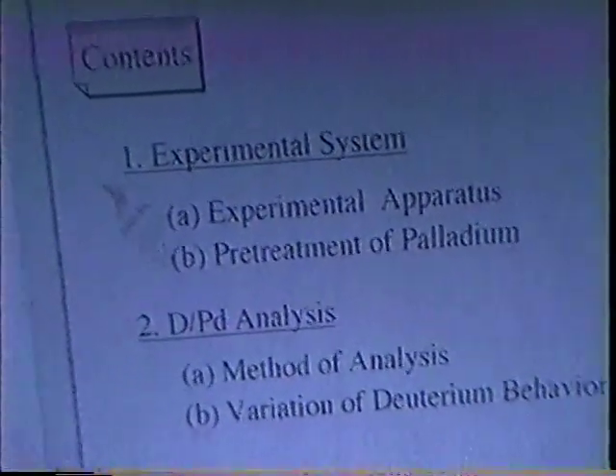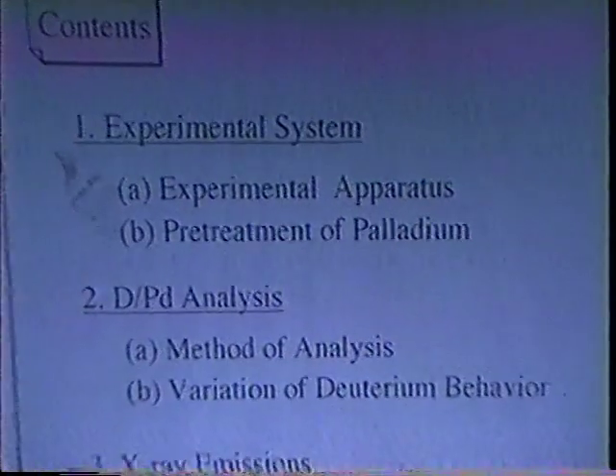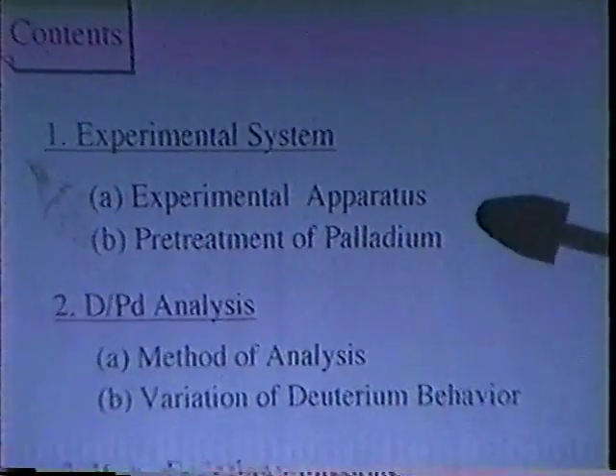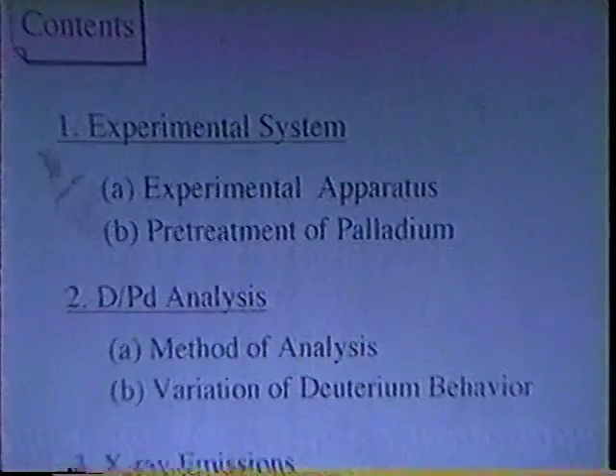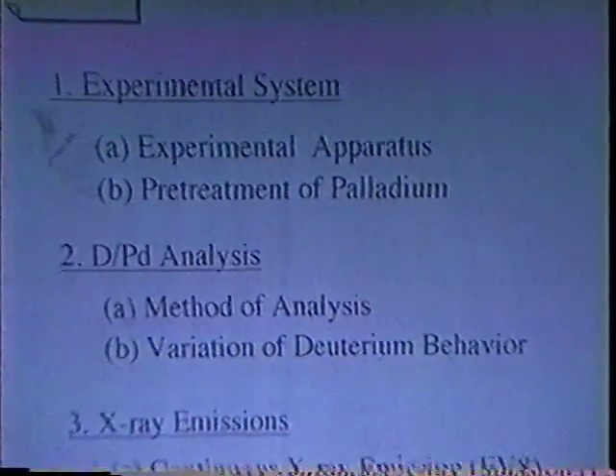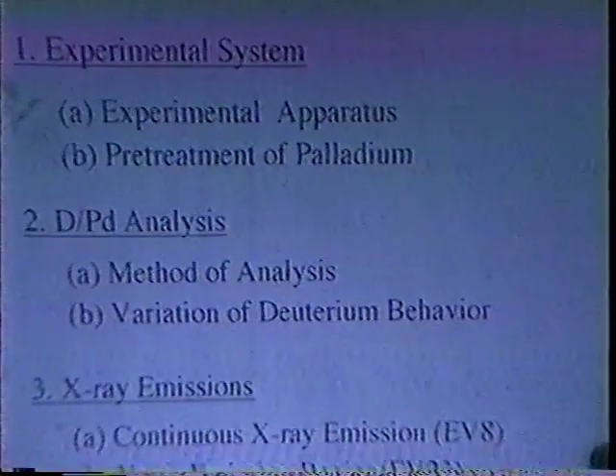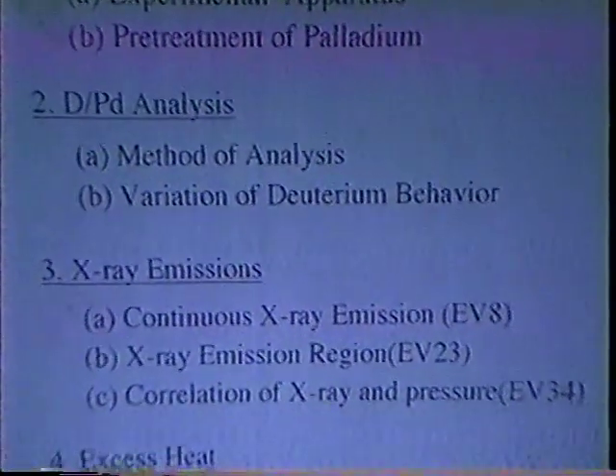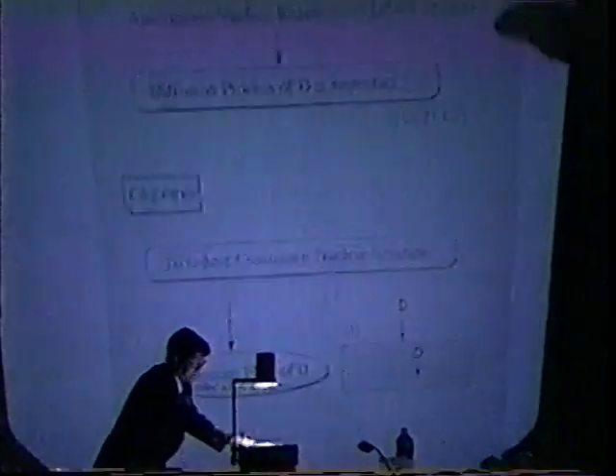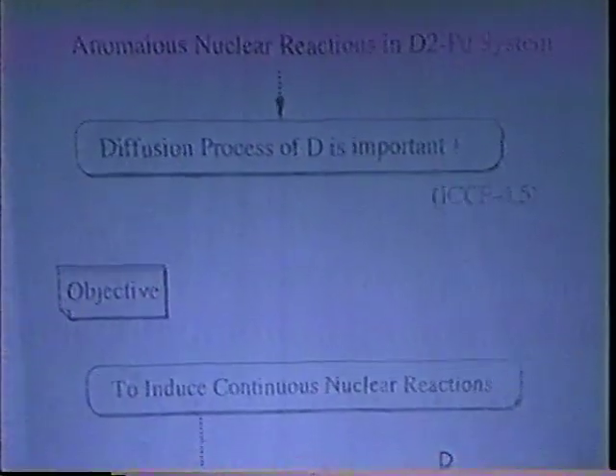Contents of my presentation is as follows. First, I will mention our new type of experimental system with intent to induce continuous nuclear reactions. Next, I will describe our experimental results on D/Pd and X-ray emission and excess heat using the developed system. We previously reported that the diffusion process of deuterium, in addition to high D/Pd ratio, is an important factor for causing nuclear reactions by the method of gas release experiment in vacuum.